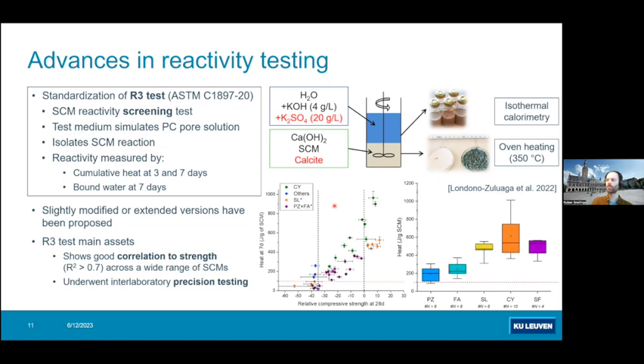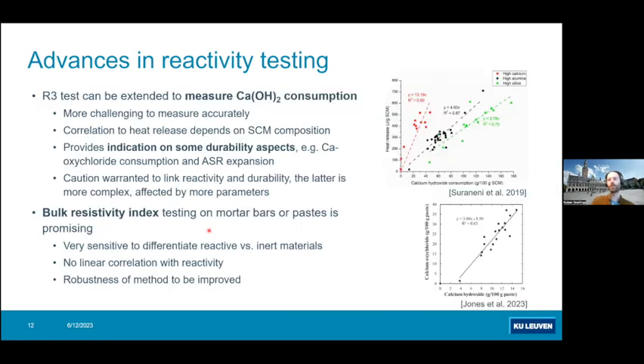There's an equivalent method measuring bound water in the same paste by a rather simple oven heating method, where you don't need a complex isothermal calorimeter. The results scale pretty well with strength development. For instance, here you can see the heat response of the test method compared to the relative compressive strength in mortar bars at 28 days. So this is a fairly good correlation between heat release results and compressive strength. And there's been an establishment of where typical materials would plot in terms of reactivity: pozzolans, fly ashes, slags, and so on. The R3 test can be extended.